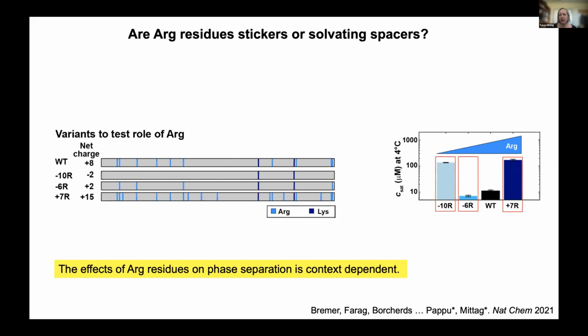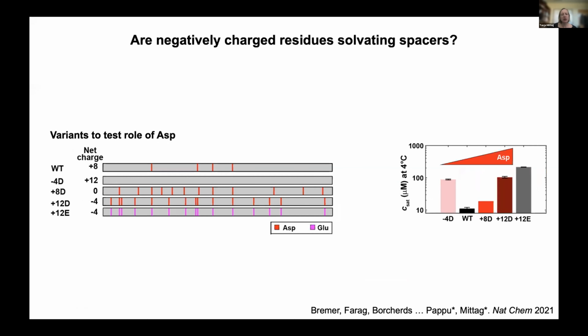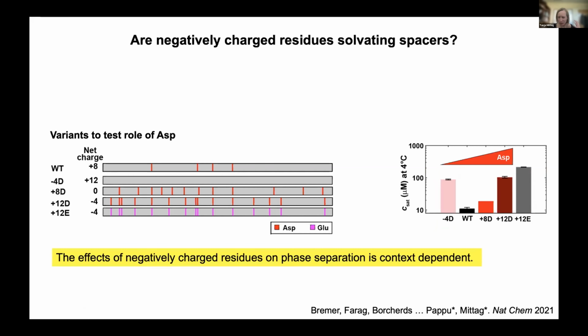But then removing all 6 intrinsic arginines really weakened phase separation. And that showed, again, this context dependence. It really depends on what's going on in the sequence, whether arginine works as a sticker or as a spacer. We saw this context dependence also when looking at negatively charged residues, where adding more and more negatively charged residues weakened phase separation. But removing all 4 intrinsic aspartate residues also weakened phase separation. So can we understand this conceptually, or do we have to look at every sequence independently to determine the influence of charged residues?